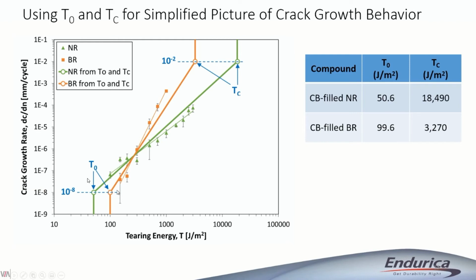then if you take the tear strength and the intrinsic strength and just connect those dots with an assumed crack growth rate of 10 to the minus 2 and 10 to the minus 8, the curve that you get actually looks a lot like the slope that you measure with a full crack growth rate test. Now you have to be careful because I don't want to represent that this is a highly accurate way to characterize the whole crack growth rate curve, but it is a way to very rapidly estimate. So in this case, for the natural rubber and the butadiene, we have these values for the threshold and these values for the tear strength.